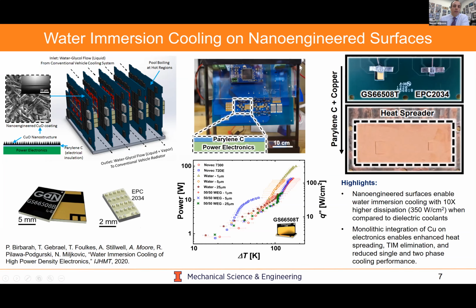We then integrate these into a 7 kilowatt, 600 volt DC-DC boost converter, which we obtain with our collaboration with Robert Pilawa. We coat it with Parylene C, and indeed, we're actually able to dunk it in water and run it at full power for days on end without any degradation. And what you see down here is actually the power dissipation per device, as well as the heat flux per device as a function of delta T for a range of different fluids.